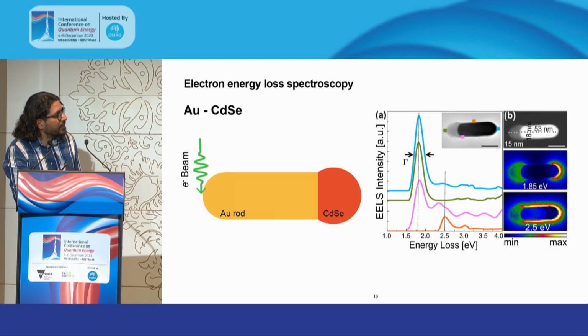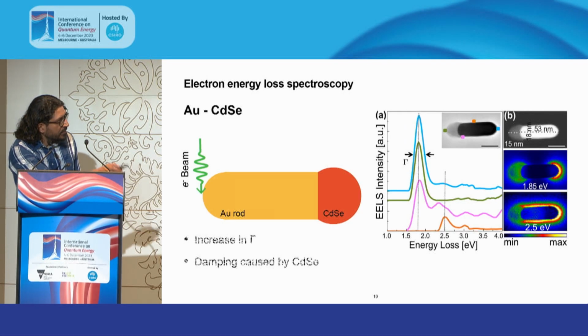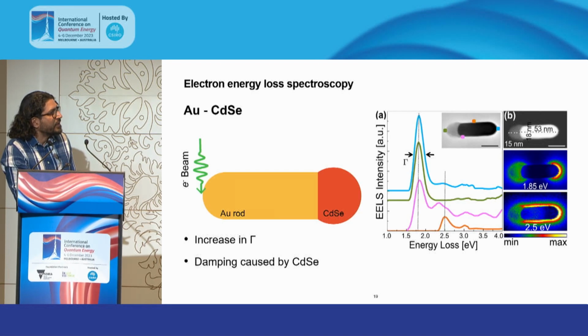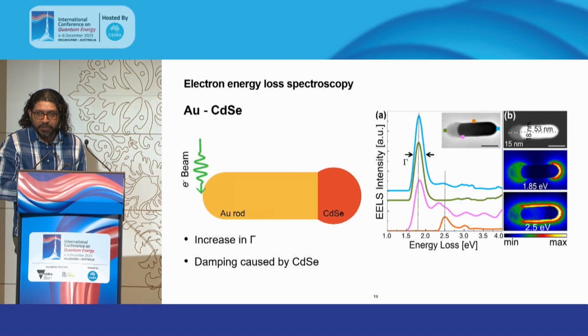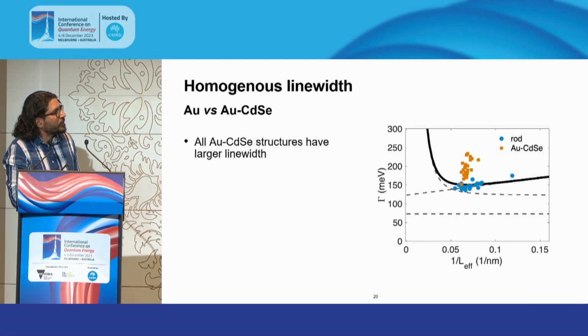This damping is manifest as an increase in the average line width, and we contend that this is due to interactions between the metal particle and the quantum dot that we have grown onto it. We repeat the analysis where we plot the line width as a function of the effective path length, and now the data for the gold cadmium selenide is shown here with the orange dots. It doesn't fit into the original understanding of plasmon damping, and there must be, therefore, a new sort of interaction.